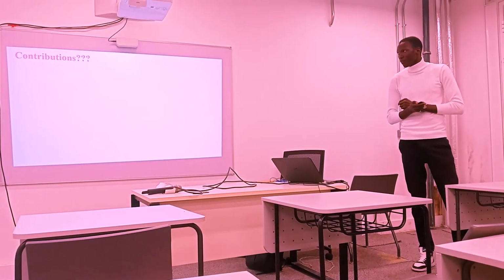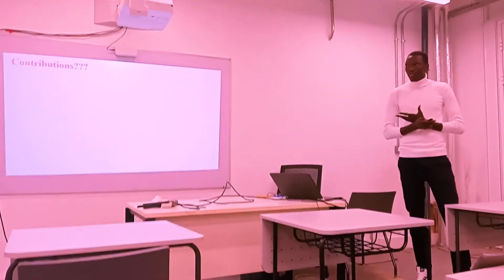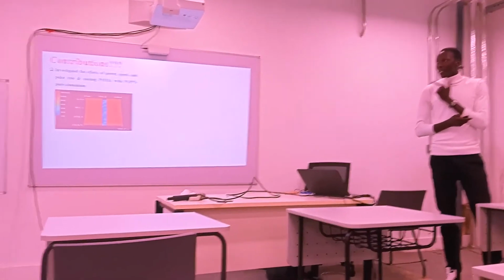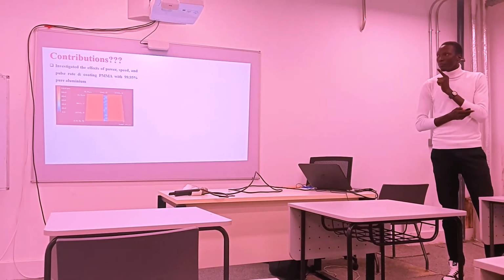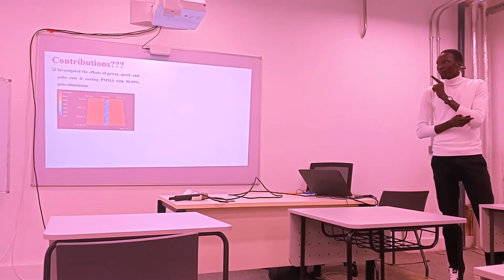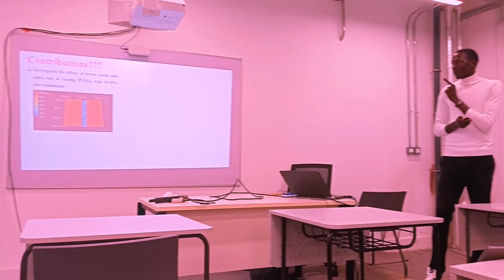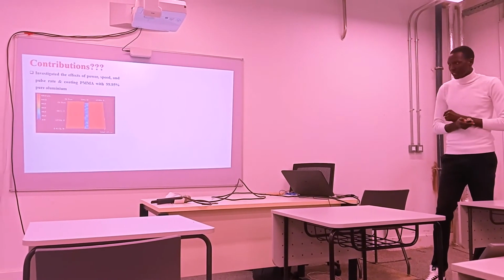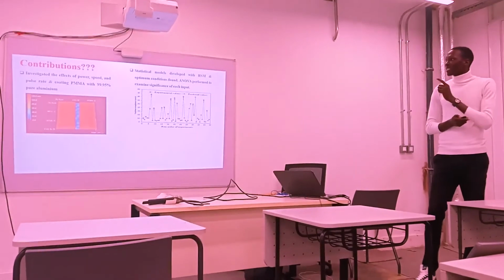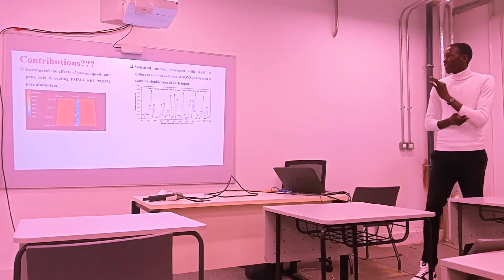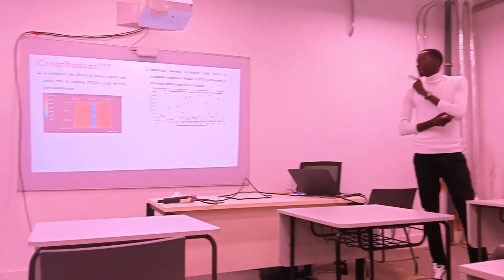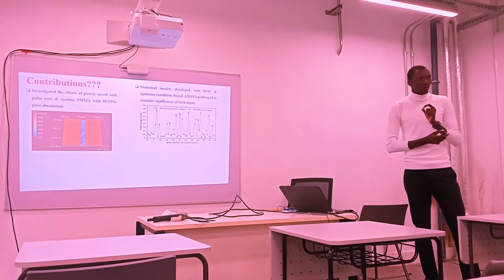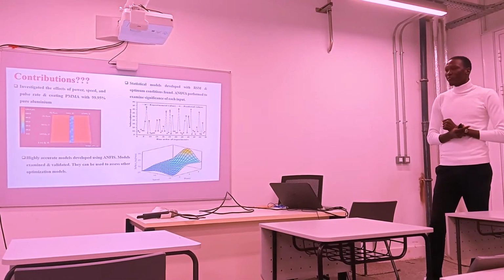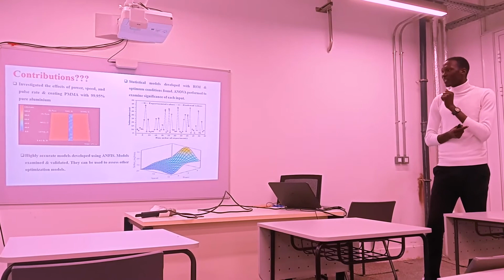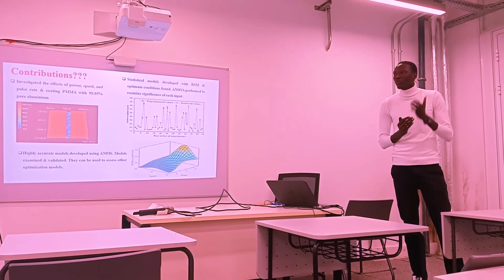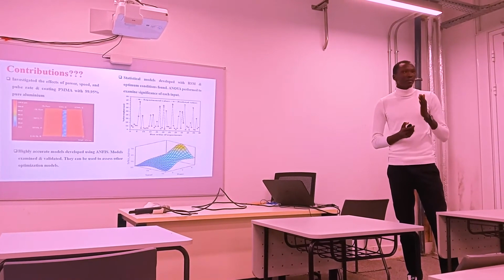PMMA substrates. And then what contributions did we make in this field? We were able to investigate the effects of power, speed, and pulse rate, and coating PMMA with 99.95% pure aluminum. I never found in literature anyone who had done this. Then we also developed statistical models with response surface methodology, and we found the optimal conditions. We performed ANOVA to examine the significance of each input. And then finally, we developed highly accurate models using adaptive neuro-fuzzy inference system. And the models were examined and validated as we saw. And they can be used to assess other optimization models.